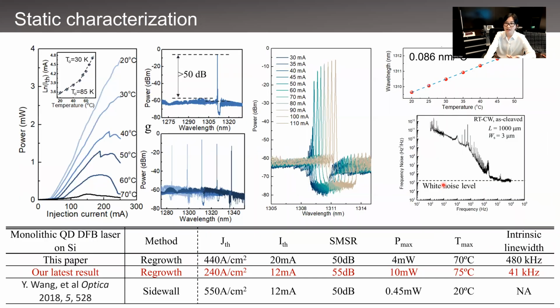So these are the temperature-dependent LI curves of a representative device, showing CW lasing up to 70 degrees C and a characteristic temperature of around 85 Kelvin in the low temperature range. We had single mode operation sustained in the ground state across a wide current range of 110 milliamps with a maximal side mode suppression ratio of more than 50 dB. So emission wavelengths from 1285 nanometers to 1338 nanometers are covered by a laser array on the same chip.